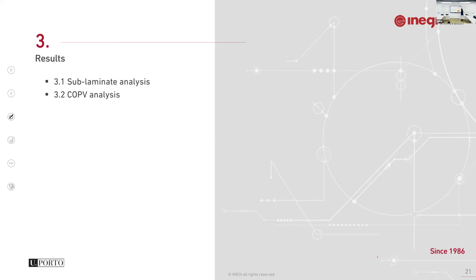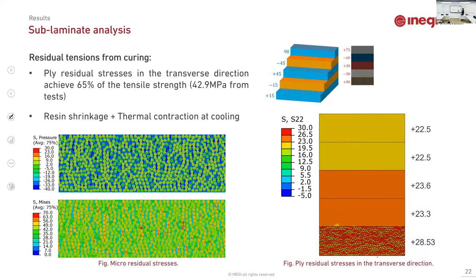Okay, let's go to the results. I will begin in another context. And this is the interesting part. First, using the sublaminate model, I simulate only the curing process. Okay. Let's say we have a typical, let's say, autoclave cure cycle. We have heating and cooling down. Let's say that this is 100 degrees. The material heats, begins to cure, and after that, cools down. What happens?